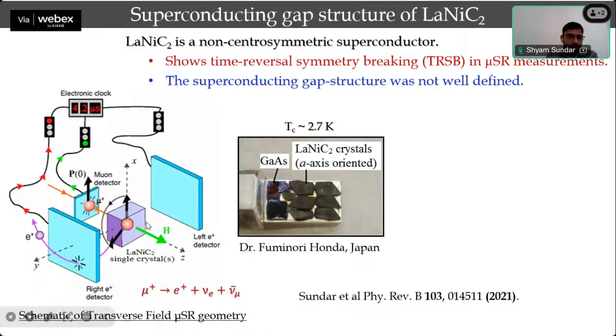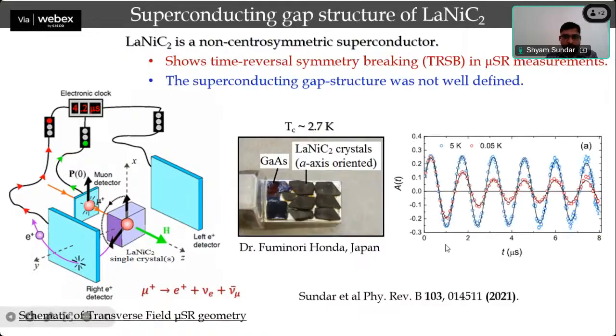So what we did is we mounted our sample here and we put in this muon beam. When the muon comes in, its spin lies in the plane of this sample, the BC plane of these crystals. Then it decays with a 2.2 microsecond lifetime into either the right or left detector. And then we got this asymmetry spectra as a function of time.